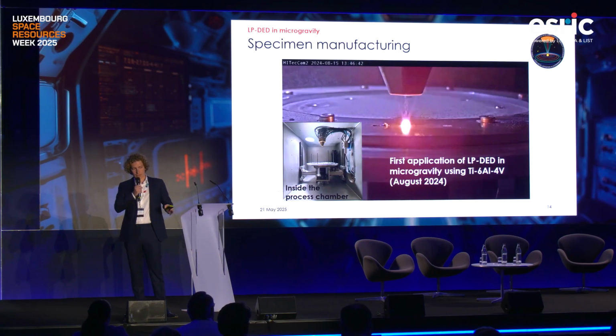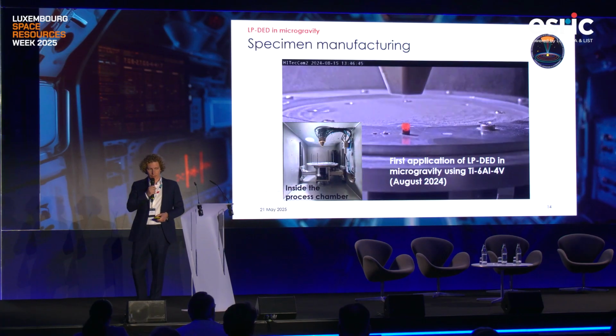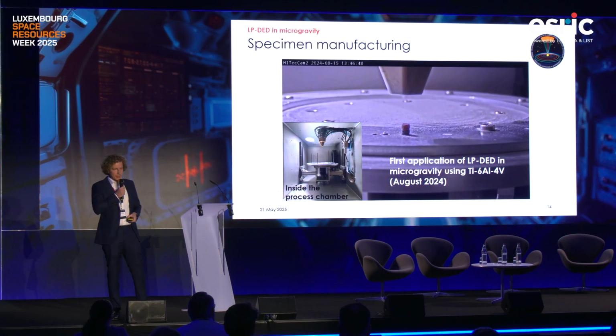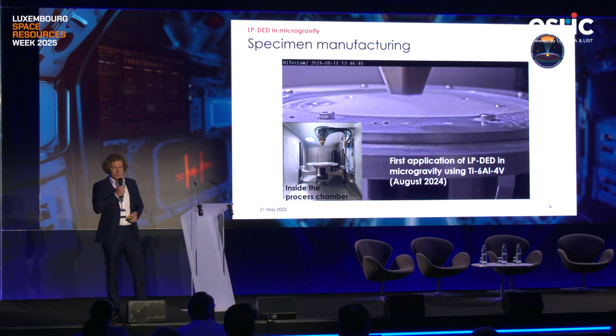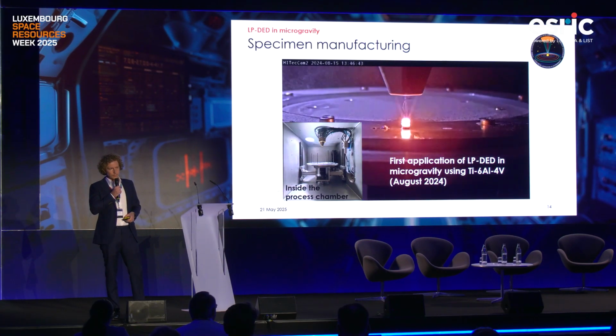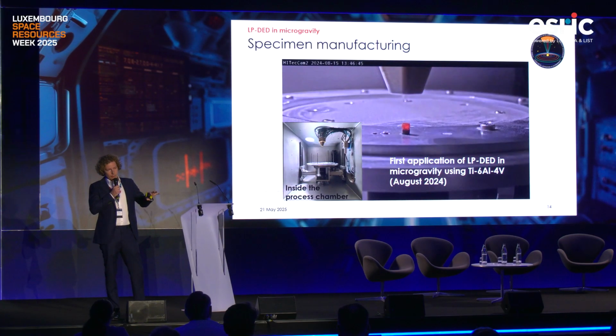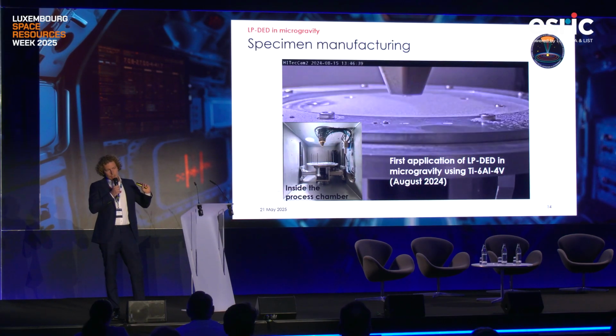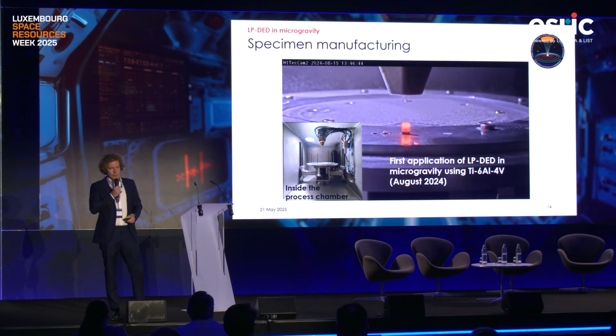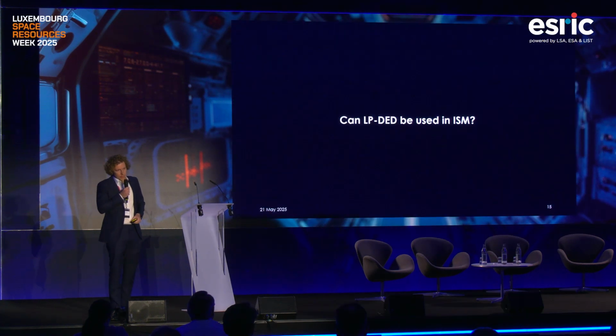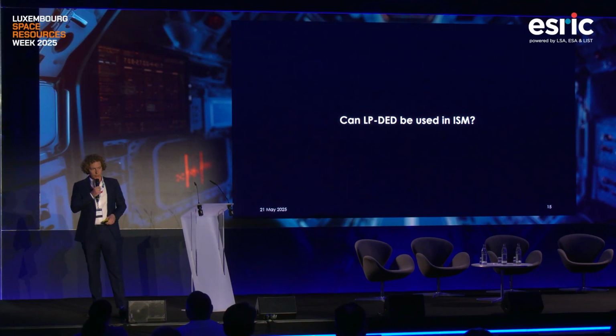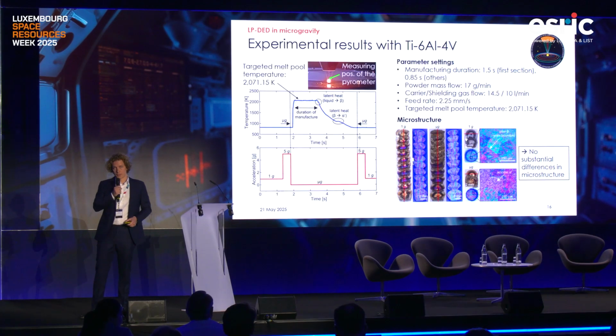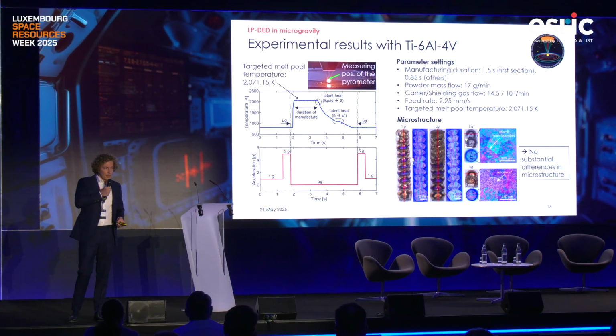So this is a worldwide first application of the laser powder directed energy deposition in microgravity. In this case with titanium 6-4. And you can see that we are only able to print a small section with the small height of the specimen, but we can do several flights to increase our height of the specimen. So the question is, can laser powder directed energy deposition be used in in-space manufacturing? And the answer is, like you have seen, yes, we can.